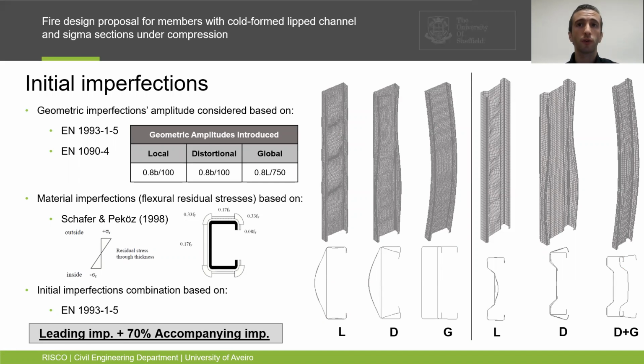Geometric imperfections were considered with the buckling mode shapes obtained with the CAST-3M and the Ruby interface. The amplitudes of the local, distortional, and global imperfections were 80% of those recommended by Part 4 of EN 1090, according to Part 1.5 of Eurocode 3. The flexural residual stresses were based on Schafer and Peköz, according to the diagram presented. Also, according to Part 1.5 of Eurocode 3, to combine these different geometric imperfections, as well as the material imperfections caused by residual stresses, a leading imperfection should be considered, with the total amplitude, and the accompanying imperfections with 70% of its value.